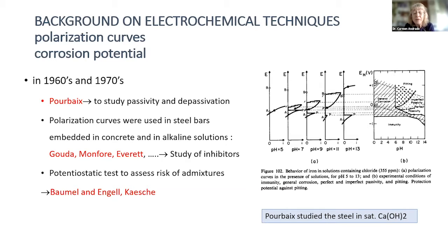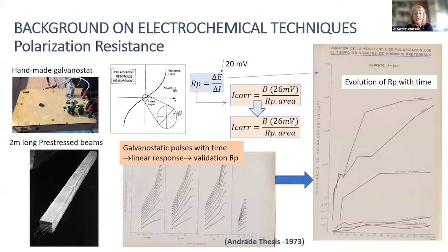They studied it at the beginning through polarization curves, either potentiodynamic, galvanostatic or potentiostatic, in order to know which concentration of chloride could develop corrosion. In my thesis, I was addressing the application of the linear polarization, the polarization resistance, and there I can mention Feliu and Gonzalez, who were also masters of David Bastidas, who suggested to me to try to apply this to concrete.